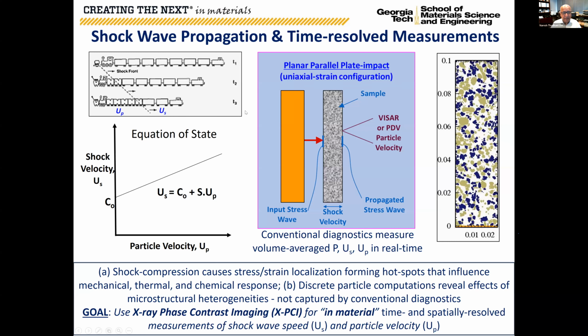Typically, when you do these measurements, an experimental process like this, where you have an impactor impacting the target, you can have stress sensors mounted at different locations, stress gauges, or do a variety of interferometry that monitors the free surface velocity at the back surface of the sample. Now all of these diagnostics typically give you a volume averaged response, corresponding to whatever is the diameter of the visar or the PDV beam, the interferometer beam, or the gauge diameter that is monitoring the propagation of the shock wave. But it doesn't give you an in-the-material response.